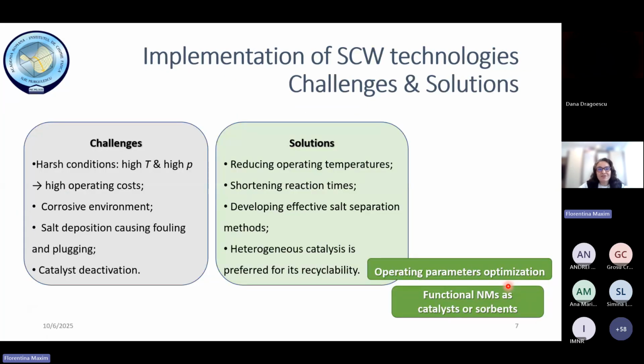Of course, like everything in life, there are some drawbacks also. The implementation of supercritical water technologies at large scale still faces some challenges, which are mainly related to the high operating parameters, high temperature and high pressure. Especially oxidation under supercritical water conditions is a corrosive environment, because all the inorganics are precipitated in the supercritical water streams. Salt deposition causing plugging and fouling of the pipes is considered a problem, of course. In the case of catalytic gasification of biomass, catalyst deactivation by the presence of heteroatoms in the supercritical water streams is also an issue.